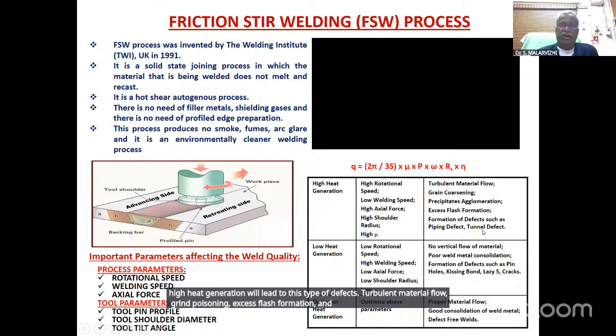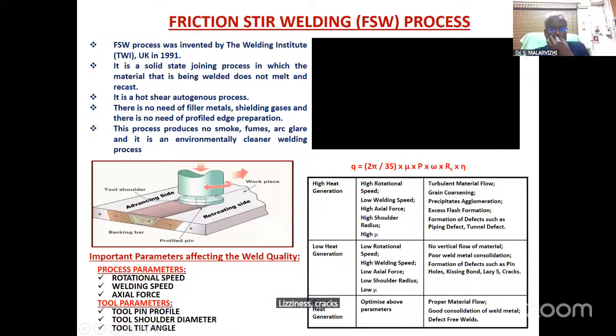You have to optimize these parameters to get the optimum weld quality. If you don't do the optimization, what will happen? High heat generation will lead to defects like turbulent material flow, grain coarsening, excess flash formation, piping defect, and tunnel defect. And if the heat generation is very low, then the material will not flow vertically, and it will lead to problems like pinholes, kissing bond, lack of fill, and cracks. So one needs to optimize the process parameters to get a defect-free weld. But as of today, for aluminum alloys and magnesium alloys, the FSW process is well established.